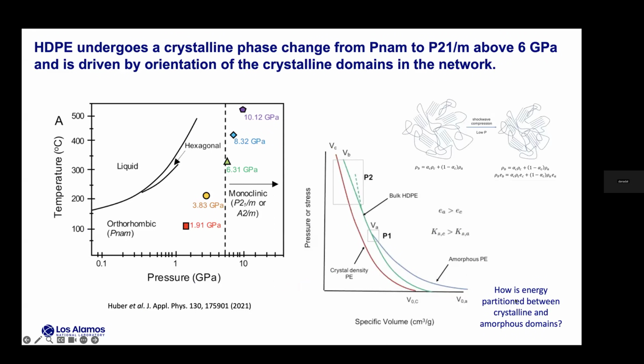The other thing that we did is we eventually started shocking within those phase transitions. So we also tried to address the question of, okay, we have Hugoniot measurements of the bulk polymer, and now we have the diffraction measurements that just look at the crystalline domains. We can look at that partitioning of compression energy between the crystalline and amorphous domains, because we can use the diffraction compared to the bulk material under shock. That's something we describe in detail in the paper, but we do see that there's more compression of the amorphous polyethylene compared to the crystalline polyethylene, much like we would expect.